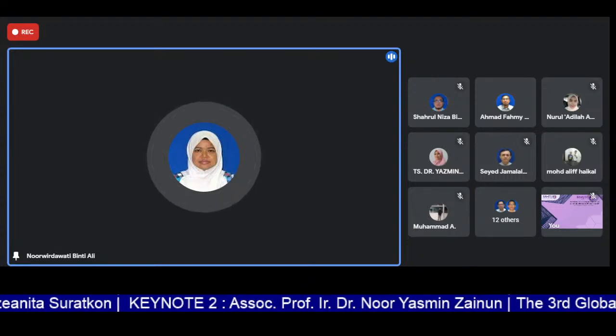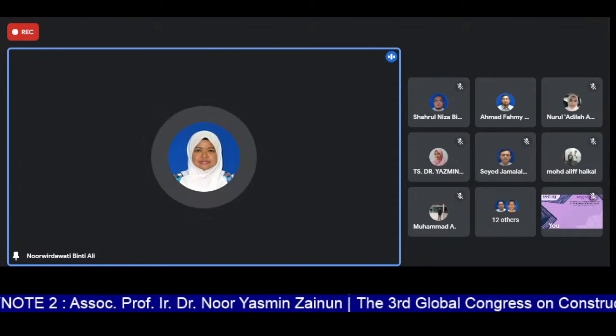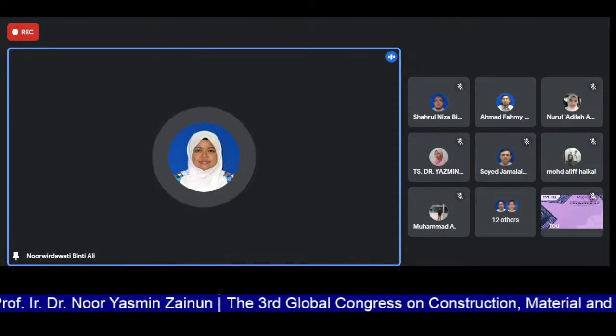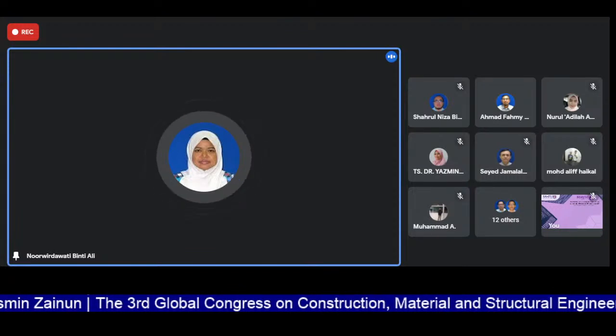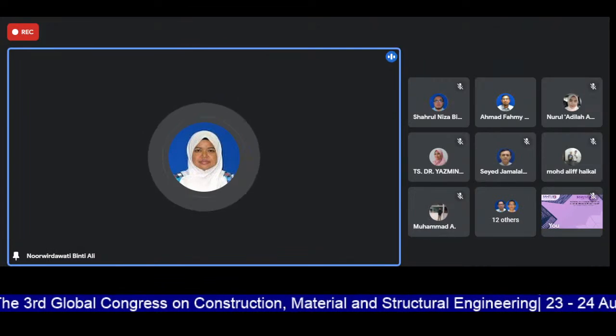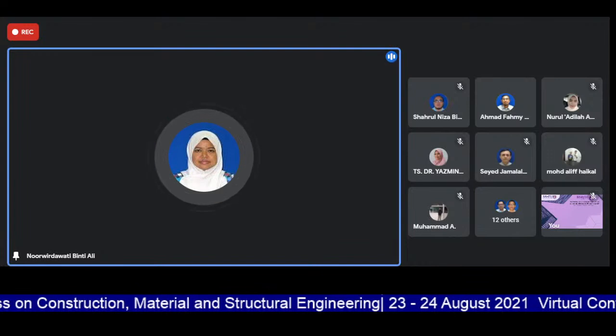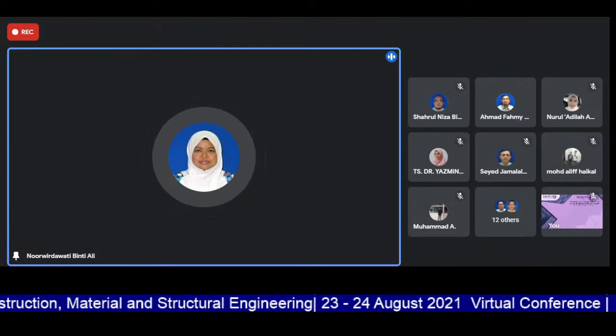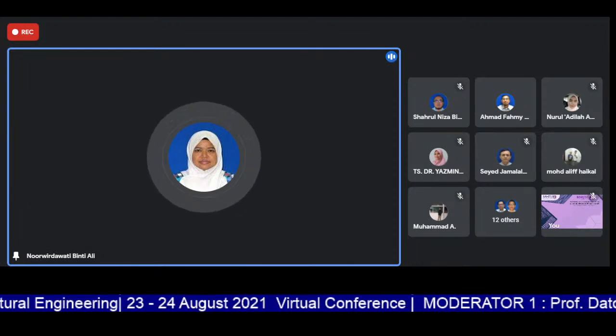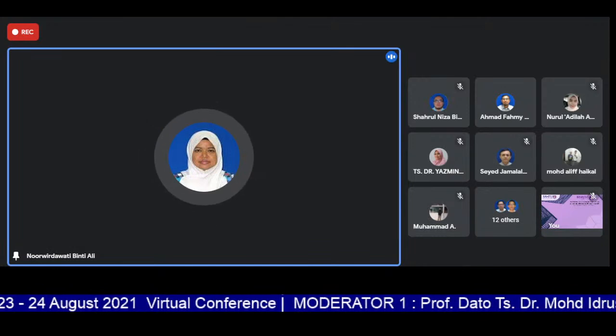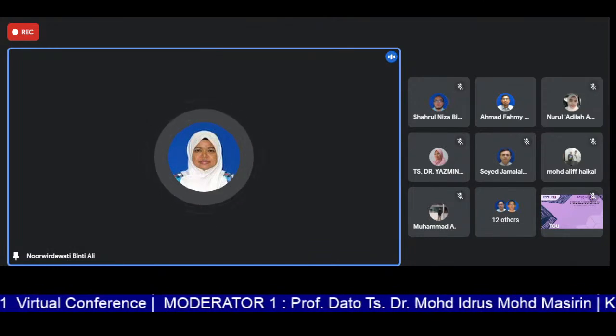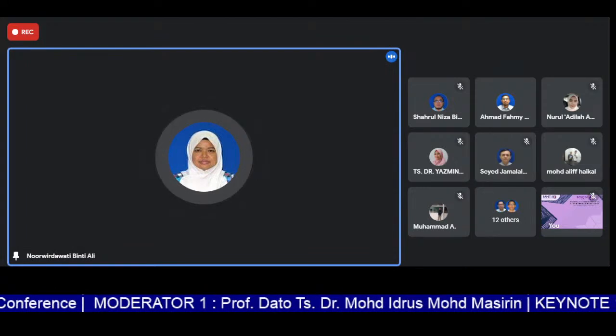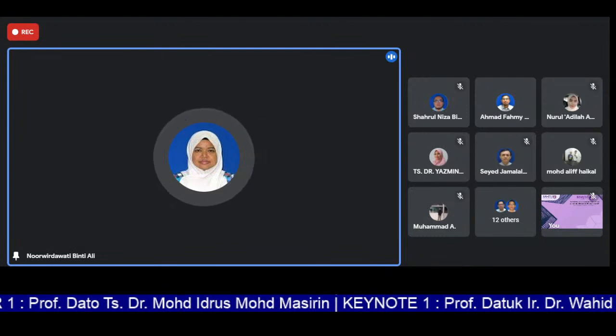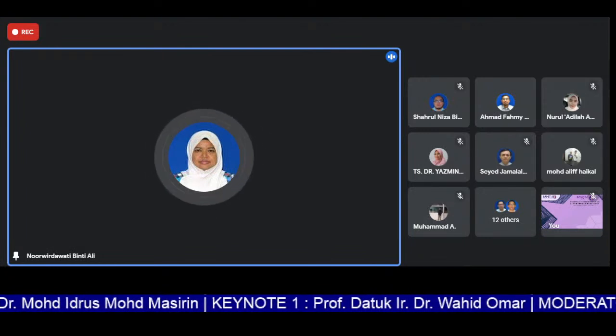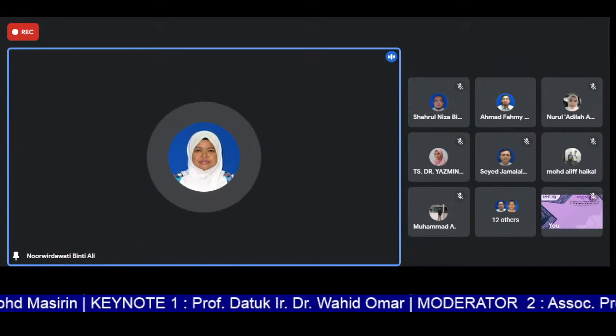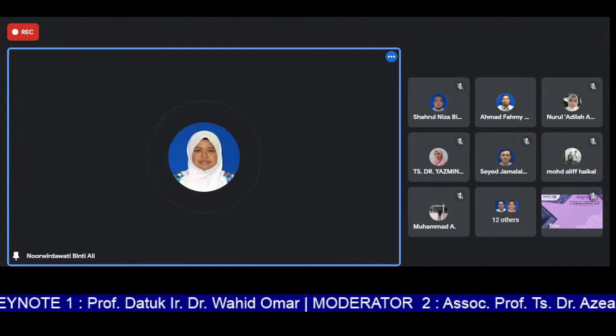The size of the opening, basically there is no specific guidance about the size of the diameter or the rectangular opening, but it is counted as the cross section area, how much percentage is lost due to the opening. From our study, the percentage of area lost due to the opening is about 60%, for the 150 mm diameter and the rectangular opening of 150 and 200 mm. This is at the opening area only, not throughout the length of the beam. At the opening area, we have lost about 60%.